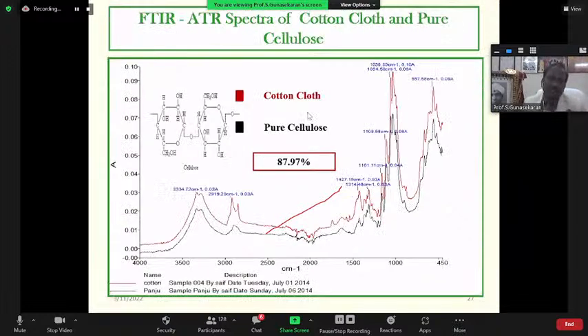We come to the next application. What is the role of the ATR technique in the textile industry? Use cotton, pure cellulose. You take a cotton cloth, obtained from Cooptex. After washing and drying, we place the cotton cloth on the IRE crystal. Using the pressure probe, we give suitable pressure without any air gap here. We are able to get the spectrum within 32 seconds. That's all, because cotton means cellulose only.